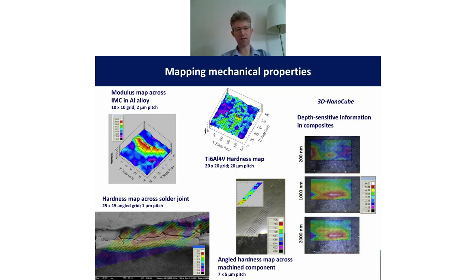On the left we can see an intermetallic compound in an automotive aluminium alloy, and that's showing essentially that it's much stiffer than the surrounding aluminium matrix. In the middle at the top is a titanium 6-4, which is a very typical material in the aerospace and biomedical fields. And when you look at this at small scale, you can start to see that the complex microstructure in this material actually gives it different mechanical property phases. So here you're getting one region with lower hardness, and here higher hardness regions. And this is down to the differences in the crystallography of the individual regions you're testing.